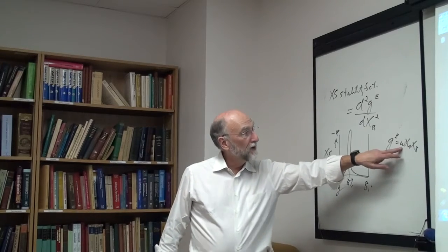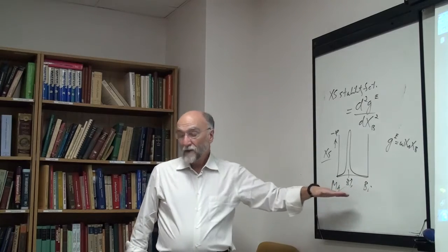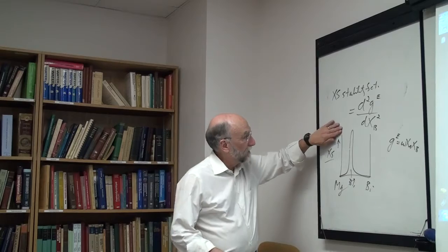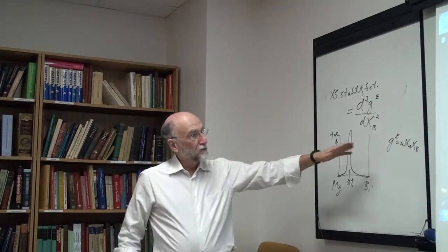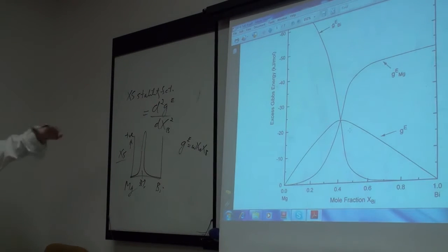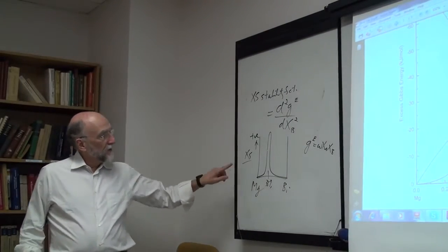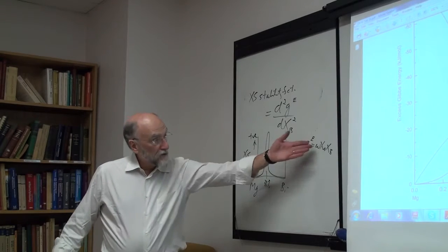If omega is positive, then the excess stability function will be negative, but constant. If omega is negative, the excess stability function will be positive. This stability means that if you have a negative Gxs that's changing, that gives you a positive stability function. This is the more stable. Obviously, the second derivative there is positive. So a positive excess stability function indicates stability relative to, say, a regular solution.